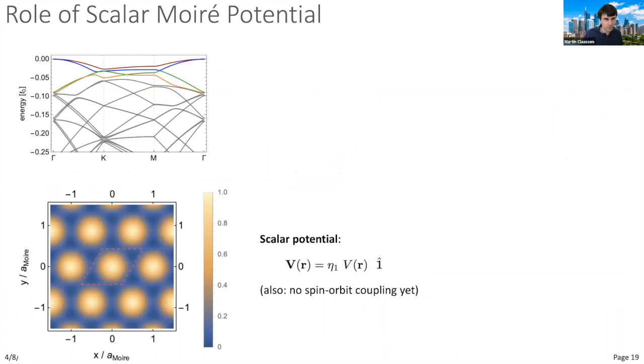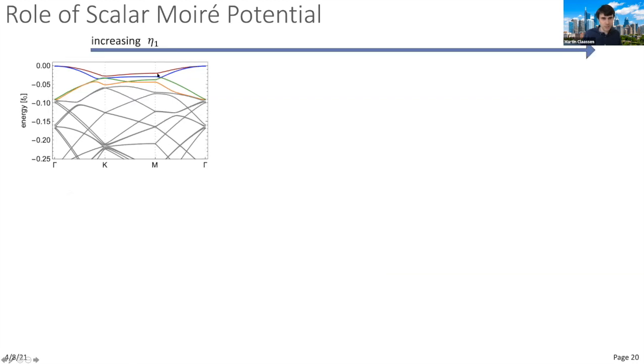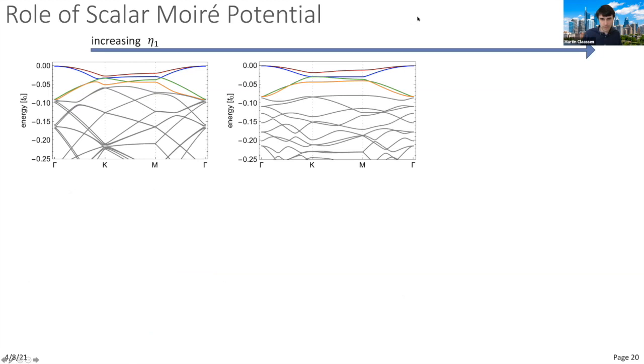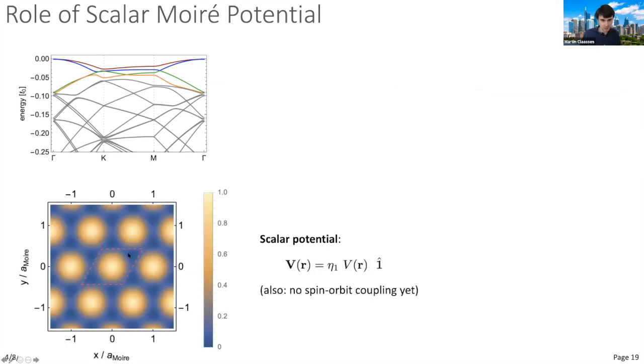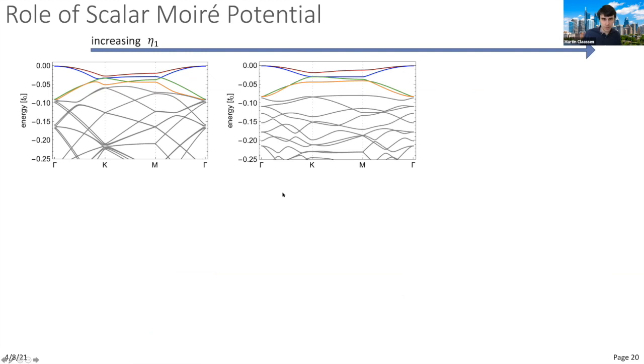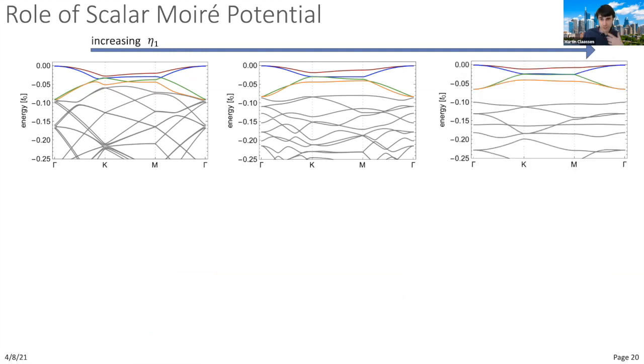What does this mean for the low-energy structure at the top of the original valence band? Considering first only the scalar potential and ignoring spin-orbit coupling: the px,py orbitals are degenerate at Γ. As the scalar potential is increased, electrons progressively localize at the honeycomb minima of the superlattice potential—now with px,py orbital character, not s-orbital character as in MoS2. So the highest valence bands form a four-band px,py dispersion on the honeycomb lattice with a quasi-flat band. Looking at orbital character, the top four bands are localized at honeycomb sites, while the fifth band has Kagome character, localized at the shoulders of the moiré potential.